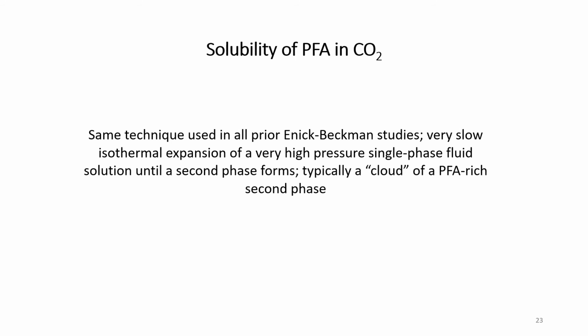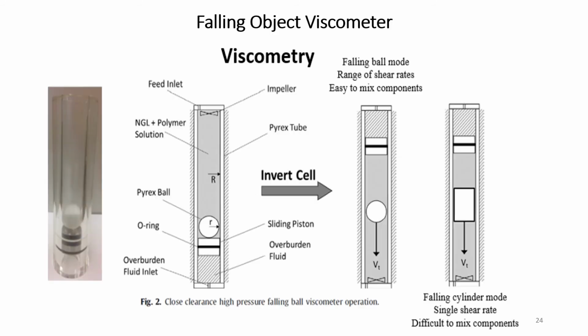I pressurize a CO2 PFA solution and mix until a single phase is formed. I then slowly expand it isothermally until the phases separate, as seen by the formation of a cloud in the clear single-phase solution. For viscosity, I use falling object viscometry, where I measure the velocity of a cylinder falling through the pressurized single-phase PFA CO2 mixture and compare it to pure CO2 under the same conditions to figure out the viscosity.